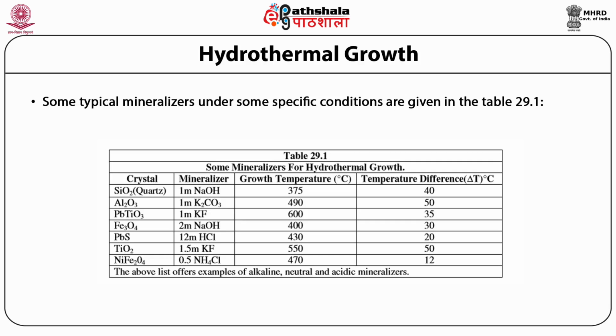Now in table 29.1 we have 4 columns. One represents the crystal, the other mineralizer, the third the growth temperature in degree centigrade, and the fourth temperature difference, that is delta T degree centigrade. The first SiO2, that's quartz crystal, for which mineralizer is 1m NaOH. The growth temperature is maintained at 375 degrees centigrade, and the temperature difference, delta T, is 40 degrees centigrade. For the crystal of Al2O3, the mineralizer is 1m K2CO3. The growth temperature is 490 degrees centigrade, and the temperature difference is maintained at 50 degrees centigrade.